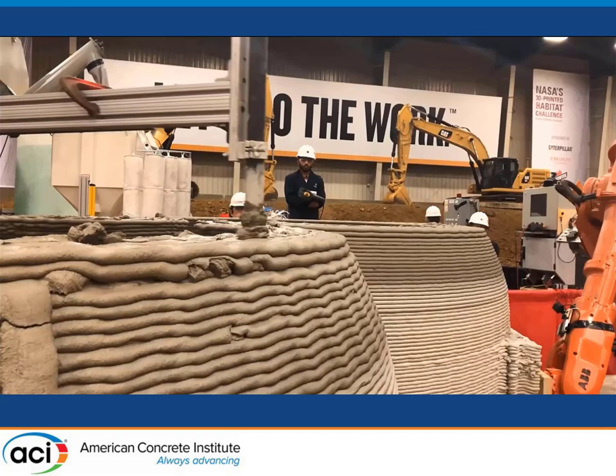The next question is, what was the strength of the material? So we did several tests. We have the compressive strength test. We also did the flexural strength test. If I recall correctly, we measured the 2 days strength of the material based on the NASA requirement. And I guess the 2 day compressive strength of the material was about 20 megapascal. In terms of flexural strength, I don't remember the value, but I could provide some documents later for you to see what the flexural strength was.